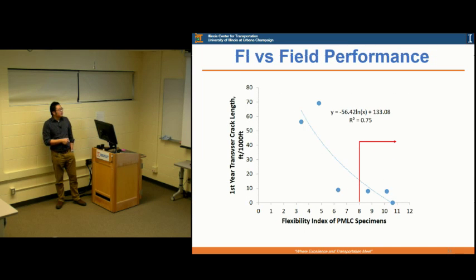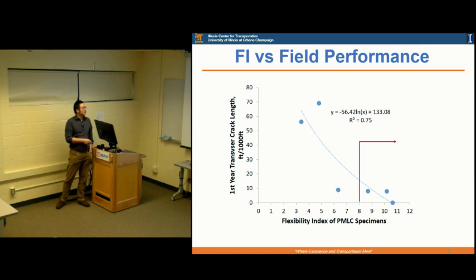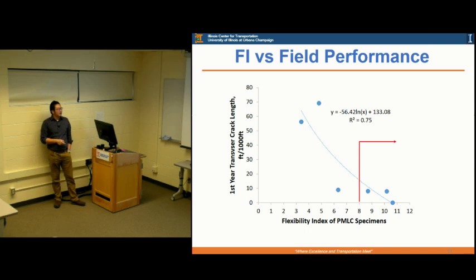If we plot the FI of the plant mix versus the transverse cracking from the first round distress survey, you can see a very clear trend: if you have a higher FI, you have much less cracking. If you have a very low FI, you end up with a lot of cracking. We try using 8 as the minimum FI, so only 3 mixes pass this threshold.